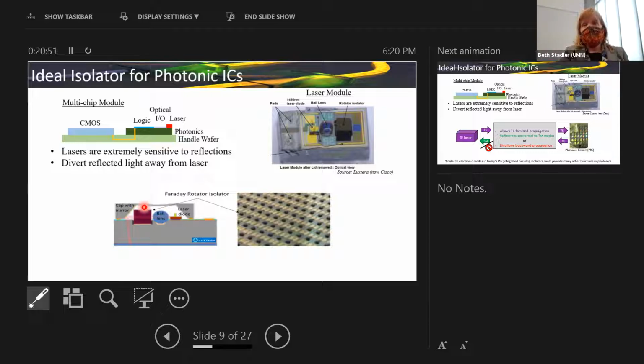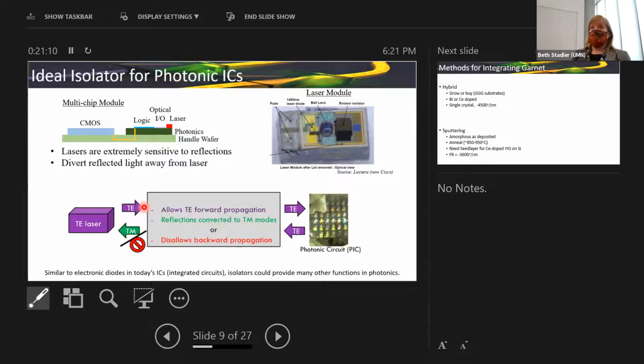The instructions for these say that if it gets demagnetized, you can put it in a magnetic field of about 4 kilooersted and it'll remagnetize. Even if it goes in-plane, because it's still one direction, it doesn't mind pointing. But if you get it realigned the way you want, it'll hold there, unless you go to a high temperature or expose it to a really high field. It's interesting that they tell you how to reset your garnet after you've made it.